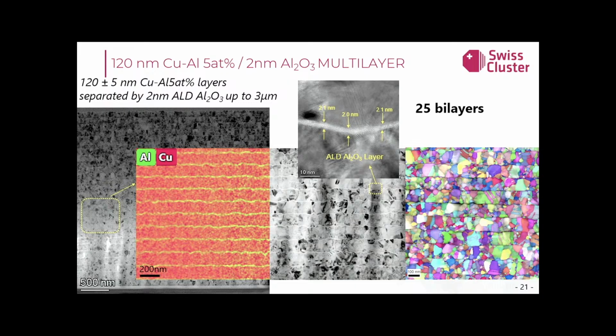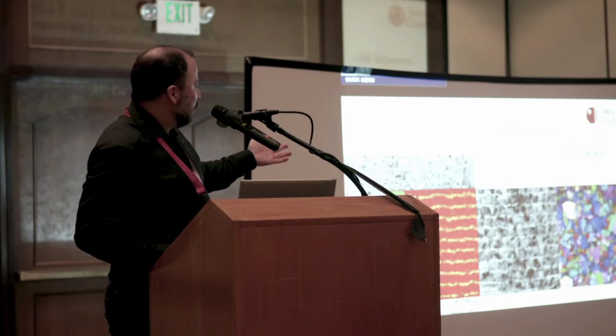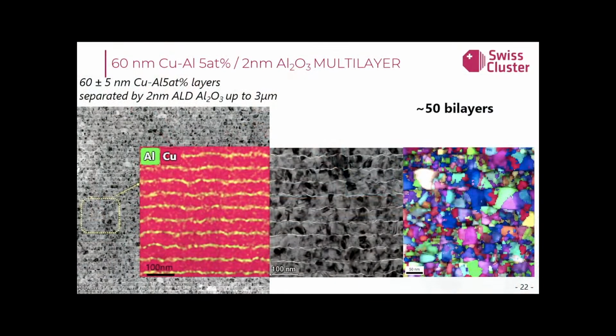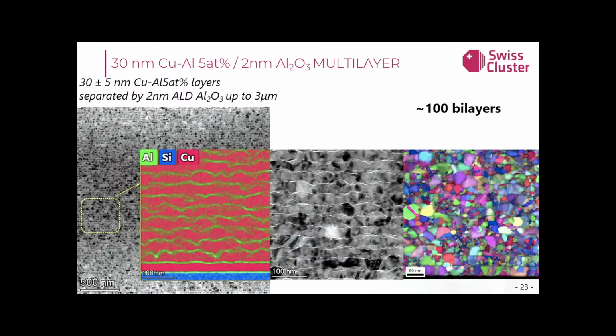If we do this every 120 nanometers for 3 microns, then we have 25 bilayers. When we do this every 60 nanometers, we obtain 50 bilayers, but still maintaining the same grain size distribution along the cross-section of the material. And then we do this for 30 nanometers to create 100 bilayers. In this way, we maintain the same grain size distribution, but we just increase the number of ALD interlayers.